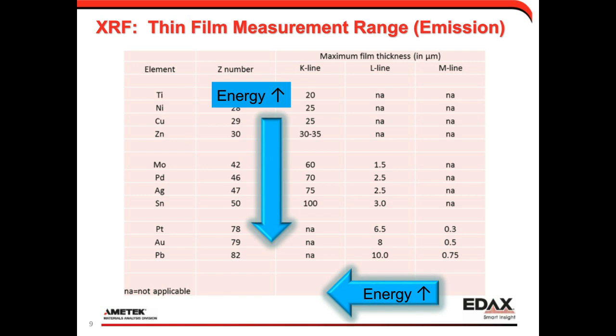If you look at the K-line column, as we run down the column, the energy of the X-rays is getting higher and higher. And in this particular case, we can measure thicker layers because the energy of the X-rays is higher, and you have more penetrating power, more escape power, so your volume of interaction is greater. You'll see on this chart, as we run to the K lines for platinum, gold, lead, these lines exist. It's just that they're very high energy. They're something on the order of 60 or 70 kV and higher, and we're running our systems at 50 kV. So we don't have enough exciting power for those.